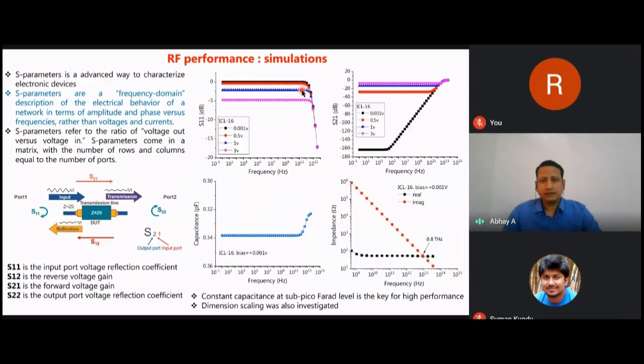So this tells us that the device has very low parasitic capacitance, and it has a value of 0.34 picofarad, and it is very flat up to 10^12 hertz frequency. And from this data, when impedance is obtained in real and imaginary parts, as you can see, it tells us that these devices have the potential to show a cutoff frequency of 0.8 terahertz.